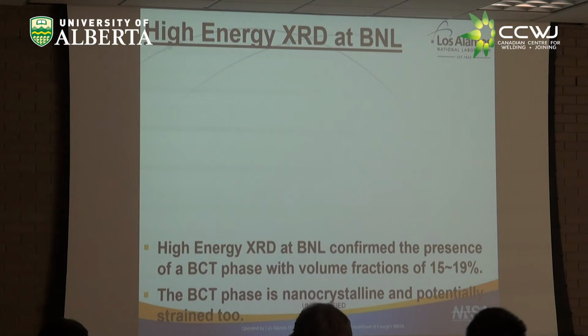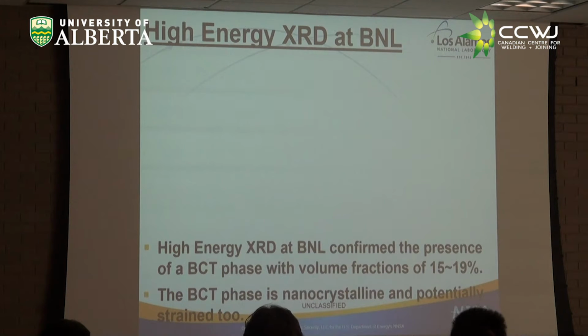If this figure were here, and I can't find this figure anymore, this is high energy XRD, X-ray diffraction, that was done by our colleague at Brookhaven. It allows you to separate in martensite, which has a body center tetragonal structure, the X-ray peaks that would otherwise overlap because of the slight tetragonality. This high energy XRD allows separation. The point to make here is that this process shows something on the order of 15 to 19% volume fraction of martensite, which we actually believe to be true, and most of that is in that speckled region we looked at earlier.